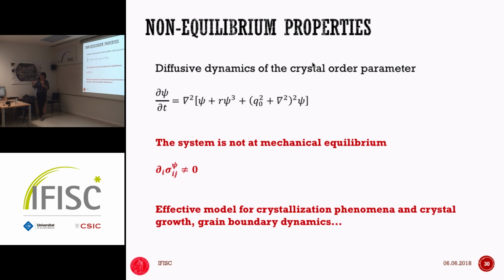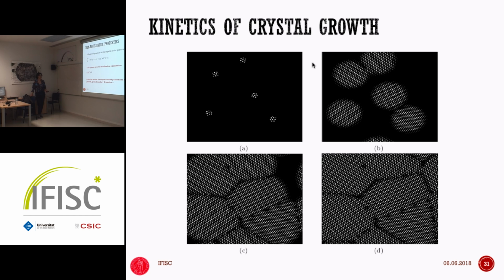So it's a little bit of a mixed situation, because from the conservation law, we only have conservation of mass, but then you want to get the momentum conservation and all the other conservation laws just from this one. So you couple them together, and you have a complicated material response. In order to separate them, you need to introduce an additional field that constrains this mechanical equilibrium. But it turns out that even if you just solve this equation, it's a very simple description that can capture, at least at the phenomenological level, quite a bit of crystallization phenomena. And it has been used extensively over the past decades to study all kinds of crystal-related phenomena.